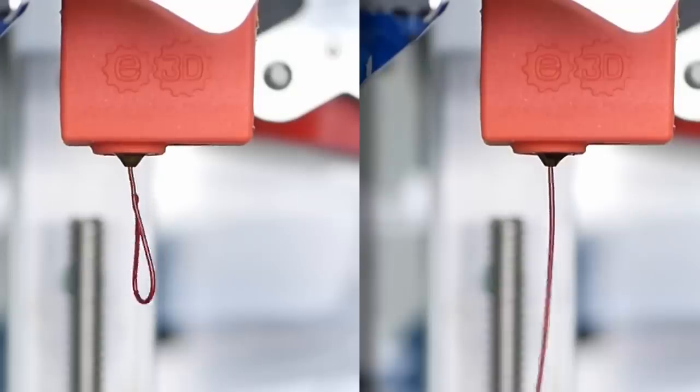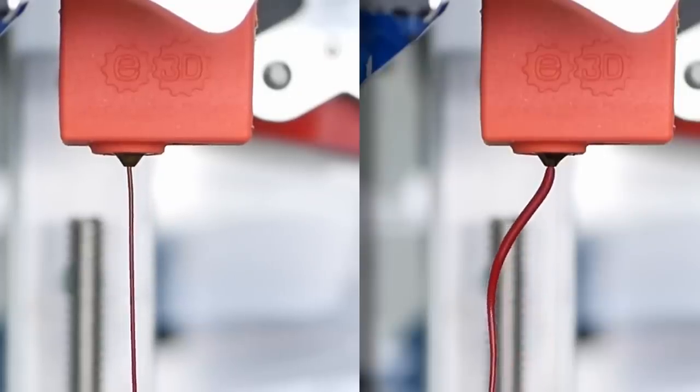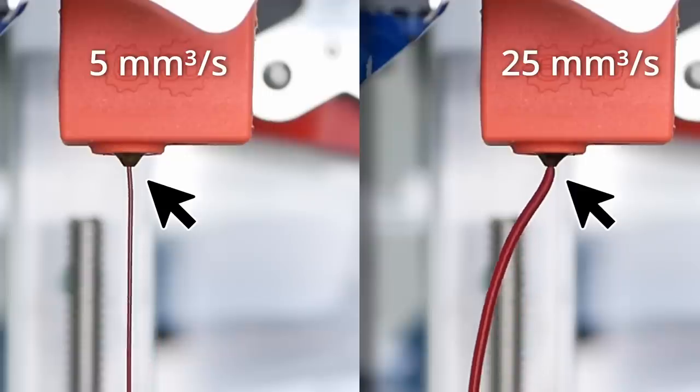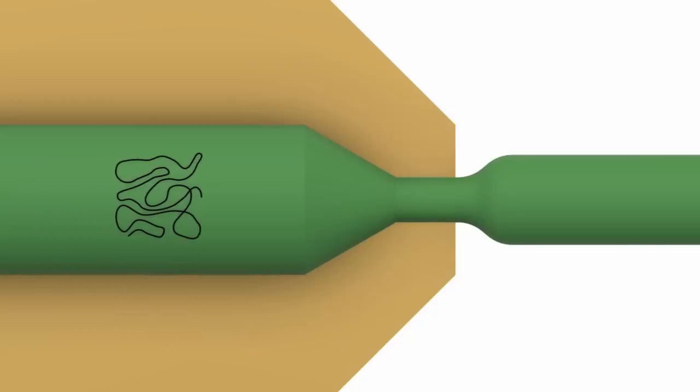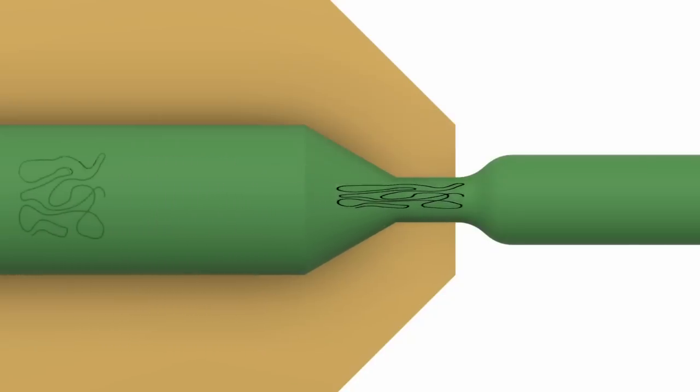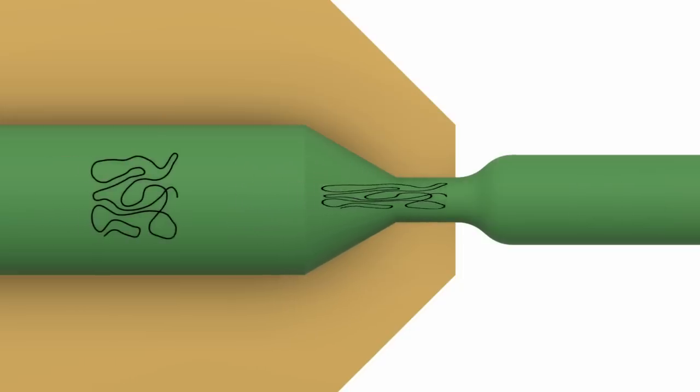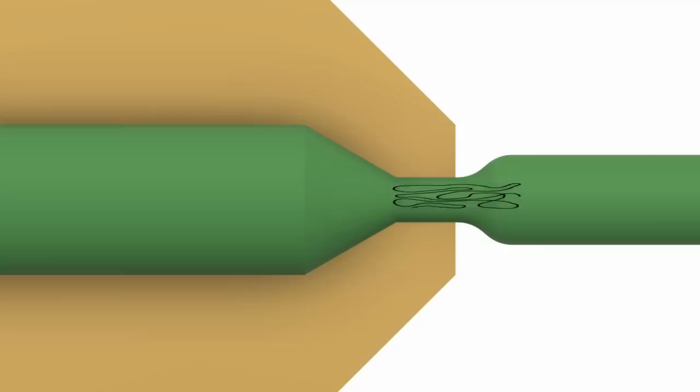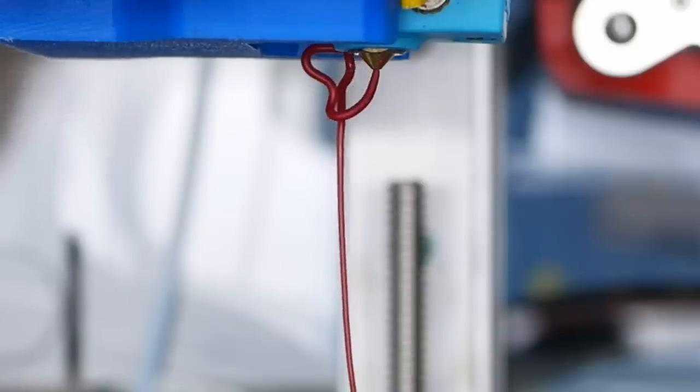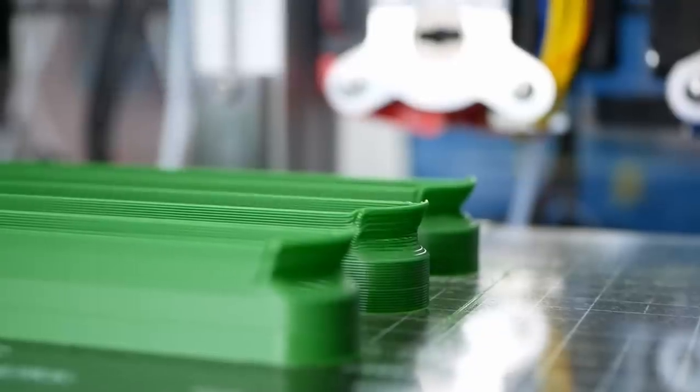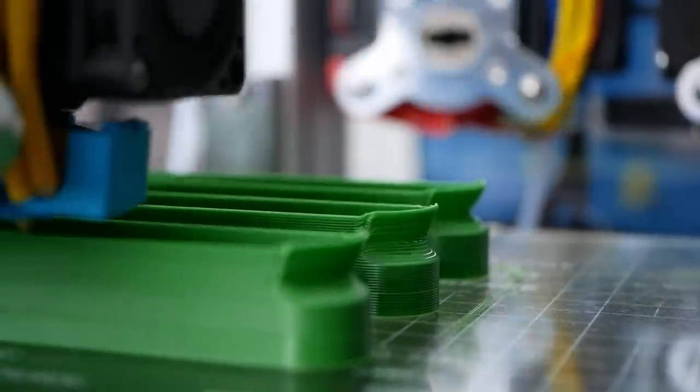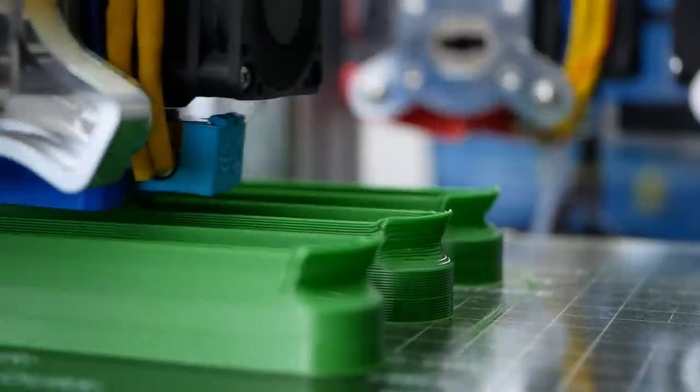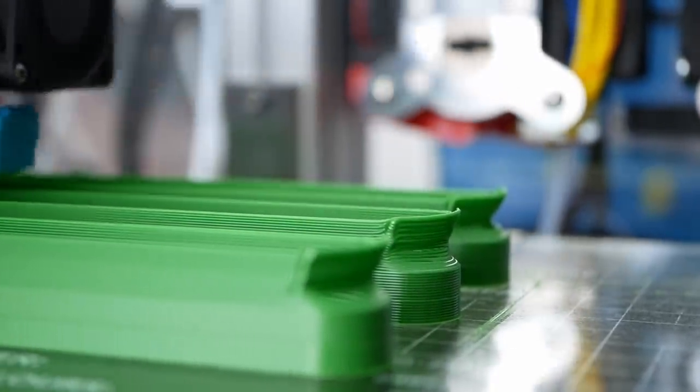If you closely watched the extrusion benchmark before, you have noticed that the filament strands significantly changed shape depending on the extrusion rate due to die swell. Die swell is the phenomenon that a melted polymer partly tries to get back to its original shape, resulting from its viscoelastic nature. The lower the viscosity before the nozzle and the shorter the time it has to pass through the orifice, the higher the die swell you usually have. Die swell is caused by the internal stresses caused during compression that try to release again. Suppose this pre-stressed material is printed and therefore basically pinned on an existing layer. In this case, the internal stresses remain in the material and cause printing problems like warping or curling on the overhangs.